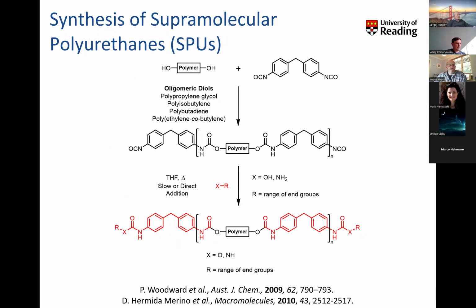The synthesis is relatively simple and scalable. We can make these materials on hundreds of grams scale now, where you take a polymeric diol, and you can vary the polymeric diol readily. You react it with a diisocyanate. I'm showing you here MDI, a very commonly used diisocyanate in polyurethane chemistry and adhesive technologies. And by using the appropriate stoichiometry of the diisocyanate to your diol, you can end cap the polyol with isocyanate units, which is still reactive.